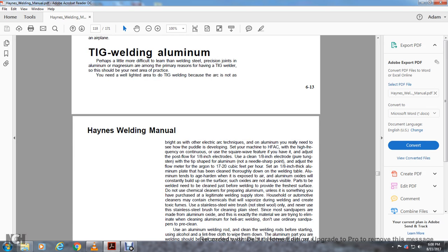Set your machine to HFAC, which is high frequency AC, using the square wave feature if you have it, and adjust the post flow. With a 1/8 of an inch pure tungsten electrode, you can clean the tip shape for aluminum with a needle sharp point.